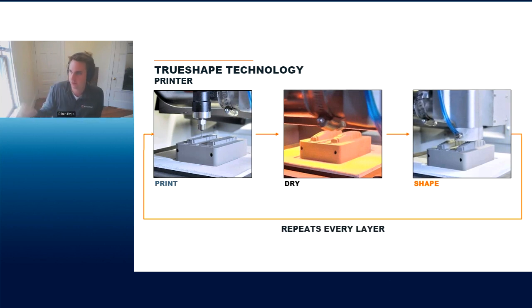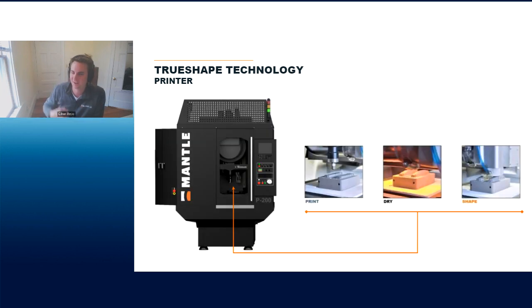This is happening over and over and over again, and also enables us to do these really, really deep ribs and deep features that traditionally you'd have to do sinker EDM for, because it's print, dry, machine, print, machine over and over and over again to build up a part, allowing us to do these really, really high aspect ratios, really small parts. I'll show a video here in a second just because it's a little bit hard to comprehend sometimes, but all three of these steps are happening inside of this one machine, all happening inside of the printer. And I'll show just a quick video here walking through the different steps.